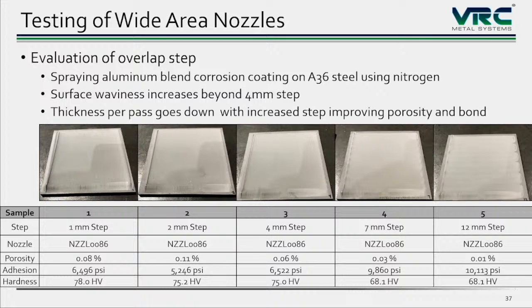As we go all the way up to 12, we do have some undulation in the surface, some waviness. However, we still have complete coverage. So if what you're looking to do is just cover a surface with a galvanic protective material, you can still do that all the way up to 12 millimeters.